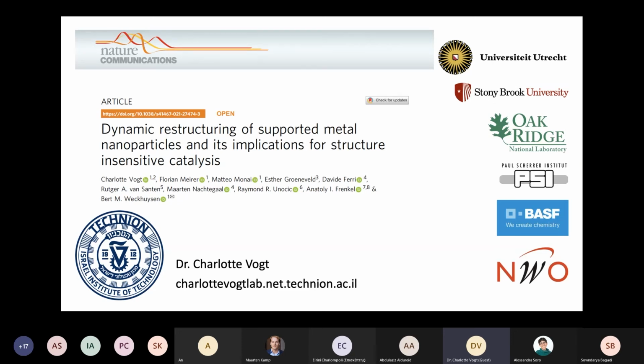But yeah, so we reduced them in hydrogen, and actually, as I tried to mention before, if we did not do that and measured electron microscopy images before we fully reduced our nanoparticles, we would really have a lot of annoyance from carbon deposition. So the carbon contamination itself surrounding the nanoparticles, or still in the cell, or maybe even in the microscope, those would deposit. So this was a very important step, to not turn on the microscope before we finished reducing.